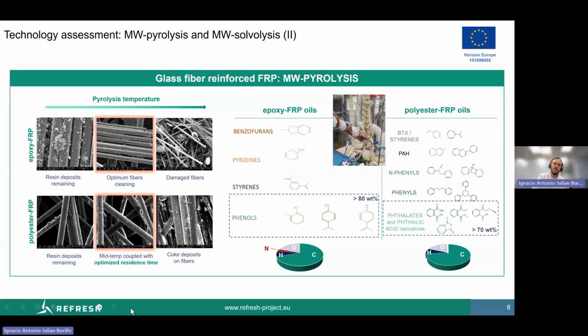So if the temperature is too low, we cannot remove the resins. If the pyrolysis temperature is too high, we damage the fibers. They start to melt. Under polyester resin, we observe more or less the same, but in this case, the residence time was to be optimized because the time that vapors spent in the hot zone of the reactor has a big impact on the quality of the oils that can be obtained.